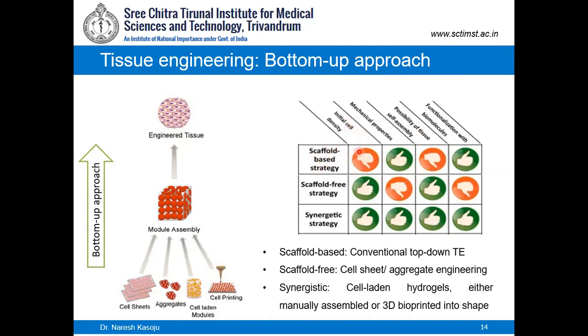So there is a problem with the initial cell density, as I mentioned. You have a porous scaffold and you try to seed it, you pour 1 ml of culture medium on top of it, which has 1,000 cells, but the medium leaks through the porous scaffold, and with that, out of 100 cells, you may lose 50 cells in that particular medium. So there is no control over the cell density. There is a loss of cell density in this case. You can fine tune the mechanical property of the scaffold, but then there is no possibility of self assembly in the conventional tissue engineering approach. You can functionalize with biomolecules by surface functionalization.